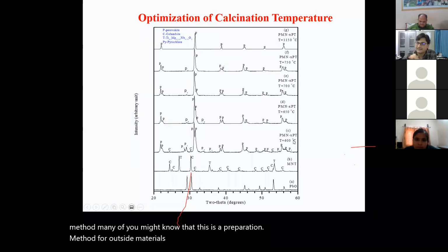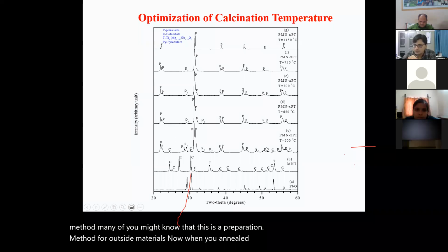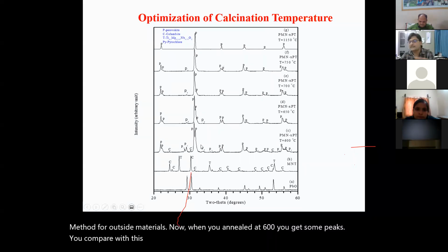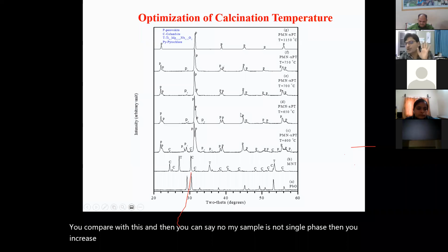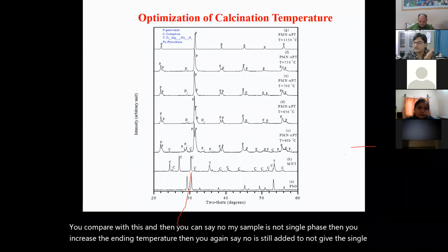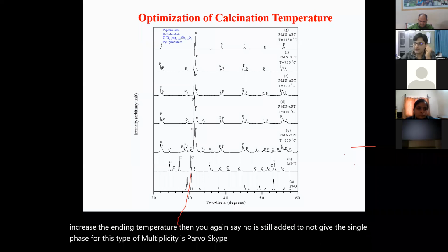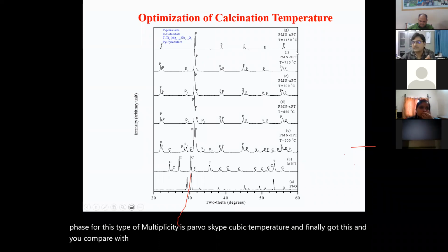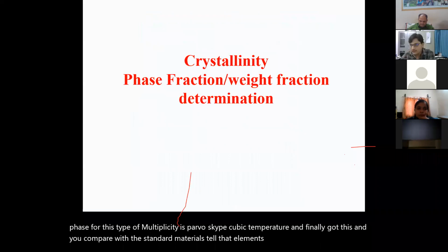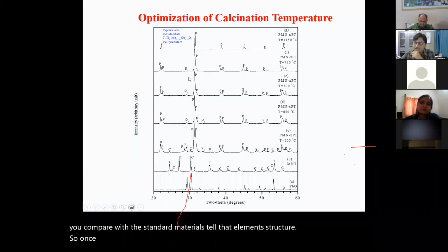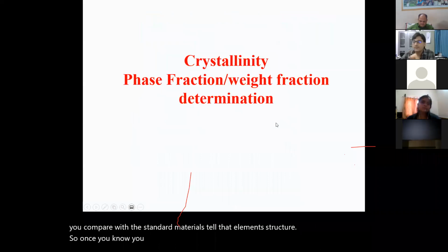Now, when you anneal at 600, you get some peaks. You compare with this, and then you can say, no, my sample is not single phase. Then you increase the annealing temperature. Then you again say, no, still I do not get the single phase. The single phase for this type of multiferroic is the perovskite cubic phase. Okay. Then you increase the annealing temperature, and finally you get this XRD pattern, and you compare with the standard perovskite material, and you tell that, okay, if I anneal my sample at 1150 degrees centigrade, then I get the single phase perovskite structure. So here you see you have 2 different phases, that you can also tell.